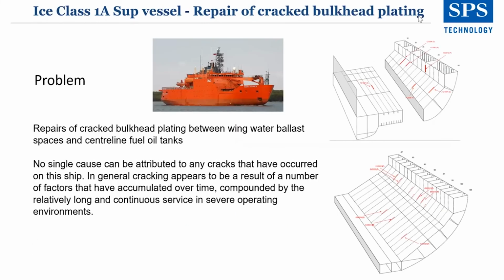The Ice Class 1A super vessel, we repaired cracked bulkhead plating. This project was brought to our attention by Lloyd's Register in 2013, following their discussions with the client regarding a life expectancy study of this already 22-year-old Ice Class vessel. The repair of the cracked bulkhead plating between the wing water ballast spaces and centerline fuel oil tanks. No single cause can be attributed to any cracks that occurred on the ship. As I mentioned before, there's various issues that can cause the cracks. Cracking appears to be a result of a number of factors, compounded by the relatively long and continuous service in severe operating environments. Even new build vessels, when they're moving into ice regions, polar regions, due to the difference in temperature, can experience cracking.